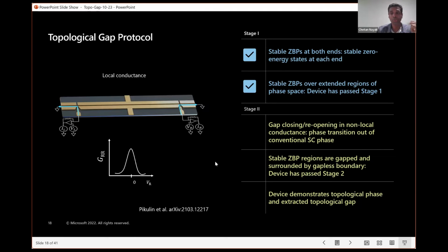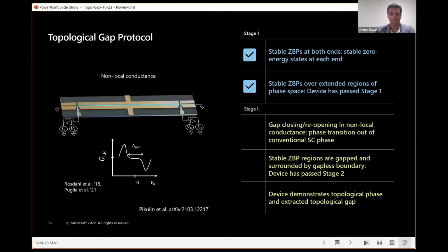In stage 2, we actually turn the problem around and say, it might be easier or instructive to look not where the system is in the topological phase, but where there's a phase transition from the trivial to the topological phase. So we look for a gap closing and reopening in the non-local conductance. And that's a sign of a phase transition out of the conventional or trivial superconducting phase.